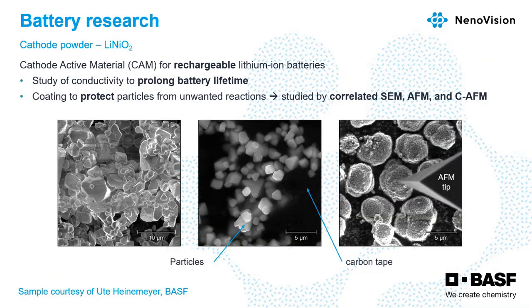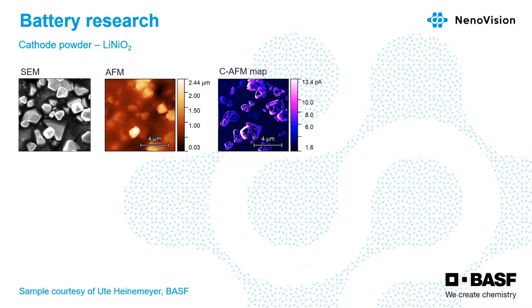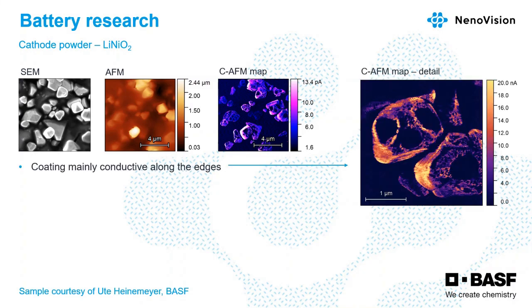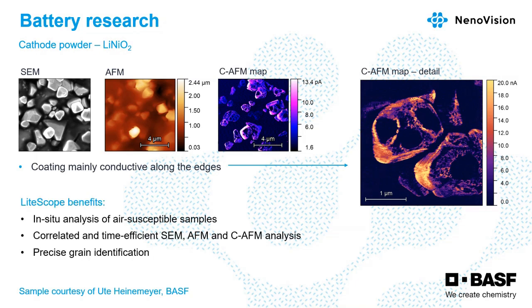So we studied correlatively SEM, AFM, and conductive measurement. And as you can see on the images, the particles were quite different with different heights. So the navigation was necessary in SEM. And so we measured correlatively secondary electrons with topography and with a conductivity map. And we found out that the coating was mainly conductive along the edges, as the detail shows. And so we were able to measure in situ the samples which are quite air susceptible, and they would otherwise oxidize if changed between the devices. And it was a quite time-efficient analysis with precise grain identification.